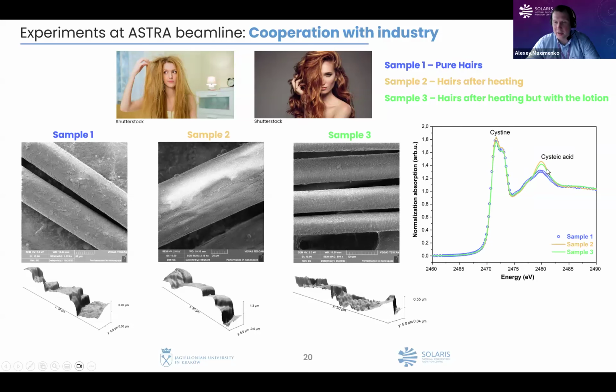And as you can see here, when you heat your hairs, cysteic acid appears in the hairs, which provides the information that they could be partially damaged. And somehow using the lotion could decrease the amount of cysteic acid in the hairs. It means that these hairs were not so damaged as without the lotion. But from my point of view, the company should work a little bit more in order to decrease the amount of cysteic acid, so it definitely does not protect you from destroying your hair. So be very careful if you heat your hairs.